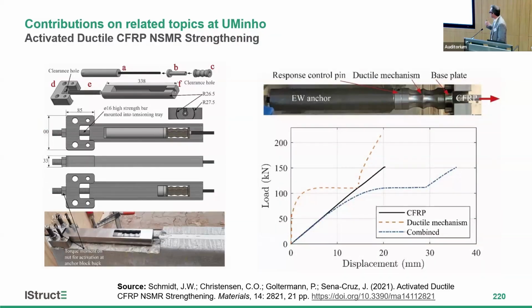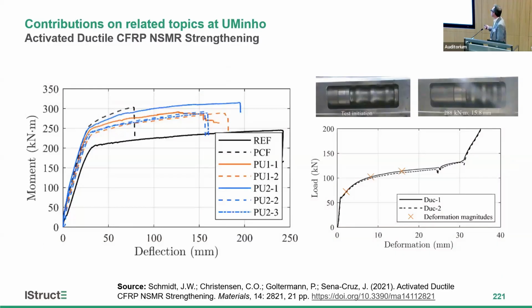Another interesting thing, in a system that I was involved with colleagues, mainly Professor J.W. Schmidt from DTU, was this activated ductile mechanism. So basically, it's a hybrid system where we have the CFRP bar, and at the end we install a spring. And this spring can be tailored in order to have a different response. So imagine this is the response typically that we have for carbon rebars. Then if we design properly this system, then we have a new response, which is ductile. And now we can have composite materials with ductile behavior, which is what we have observed here with these full-scale beams, and you can see that we could have a very ductile response of the beams, even pre-stressed, but now with this ductile activated mechanism.